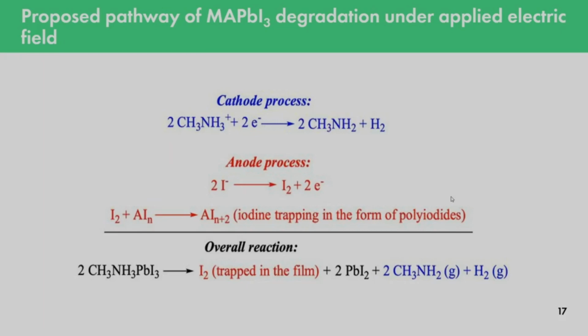Thus, after all these measurements, we were able to propose the pathway for electrochemical degradation of pristine, not in a perovskite solar cell, but pristine methylammonium lead iodide material, which includes reduction of the organic cation on the cathode with the formation of mostly volatile products, which leave the film and thus make the whole process probably irreversible. At the same time, at the anode, we most likely have oxidation of iodine anions into molecular iodine. But if we believe the TOF-SIMS measurement, this iodine mostly remains in the film, probably in some form of polyiodides, which stays trapped in the film, most likely.